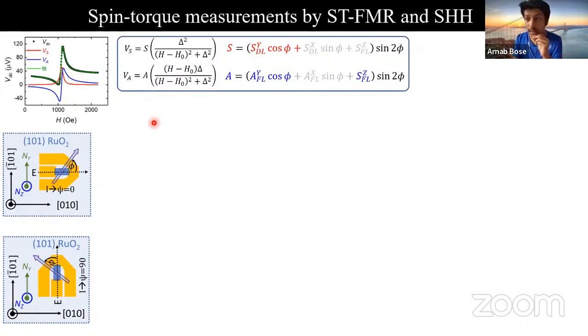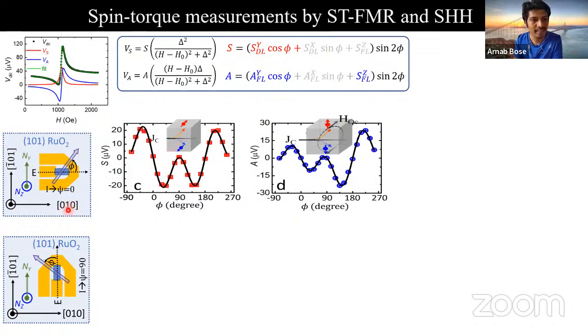So here we are doing STFMR. Now I will show the results when we are running current along psi equal to 0 axis and psi equal to 90. Just to remind you, we are applying microwave current, measuring DC voltage by sweeping an external magnetic field at an angle phi. We measure the DC voltage, which is split using symmetric and antisymmetric Lorentzian. We repeat the same experiment for different values of phi to get the angular dependence of this symmetric and antisymmetric Lorentzian, from which we can quantify different types of torques. So this is a result when we run current along this direction, the 010 axis. So already we see a clear distinct difference in the symmetric and antisymmetric Lorentzian, the angular dependence of S and A.